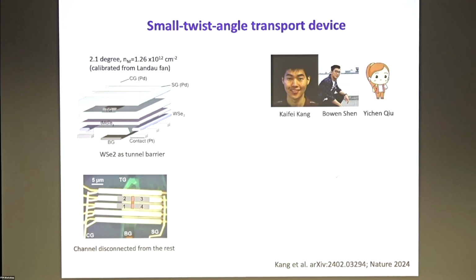It turns out that it's actually pretty challenging because the system tries to relax to this ferroelectric structure at very small twist angle. But the heroic efforts of this group of people here really realized this device. It's a device with a pretty complicated structure here. Let me walk you through a little bit. It's a 2.1 degree device with a moiré density about 1.2 times 10 to the 12 per centimeter squared, and it's calibrated from the Landau fan of this device.